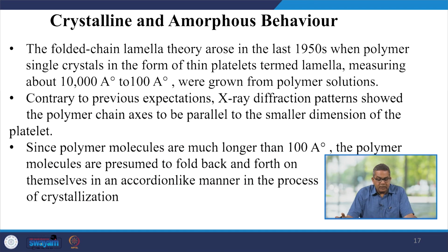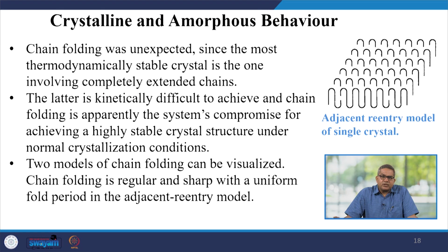The folded chain lamella theory arose way back in 1950 when polymer single crystals in the form of thin platelets, termed lamellae, were found. These measure about 10,000 angstrom to 100 angstrom. They were grown from the polymer solution. Previously people had expected otherwise, but contrary to that, X-ray diffraction patterns showed the polymer chain axis to be parallel to the smaller dimension of the platelet. Now, since the polymer molecules are much larger than 100 angstrom, they are presumed to fold back and forth on themselves in an accordion-like manner during the process of crystallization.